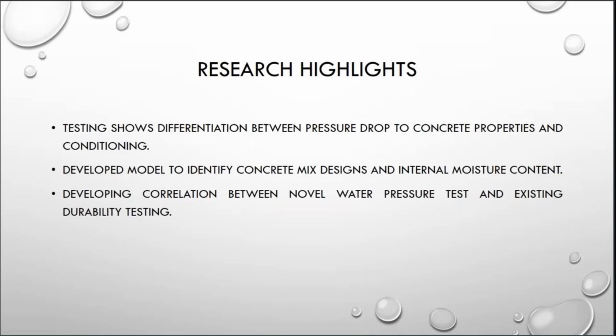In a dry sense, basically getting some type of heater on the surface, or different ways we're talking about. Amer has some ideas of even using pressure, that type of thing, to remove that water. So you can dry the concrete, run this test, and see how the water penetrates. Likewise, you can wet the surface by ponding it, have it initially wet on the surface, and also run a test. And with future testing, we're hoping to use those to get a sense of what the concrete material is like.